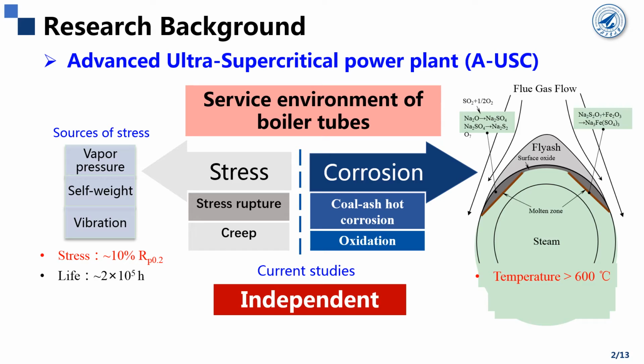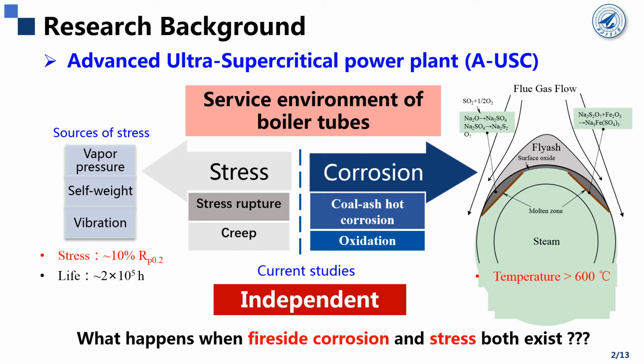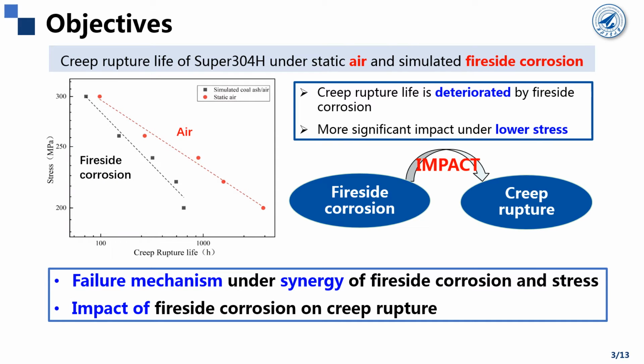Unfortunately, in current studies, the failure caused by stress and the failure caused by corrosion are investigated independently. So the problem is what happens when fireside corrosion and stress both exist. In our early study, when we compared the creep rupture life of Super 304H in static air and in the simulated fireside corrosion, we found that the creep rupture life can be greatly deteriorated by fireside corrosion, and it becomes more significant under lower stresses. So the objective of this study is to find out how fireside corrosion impacts the creep rupture behavior.